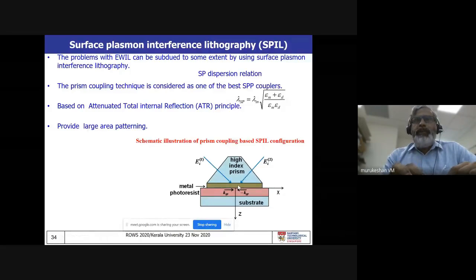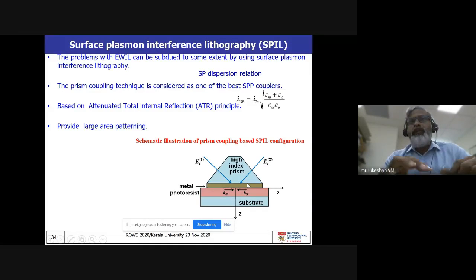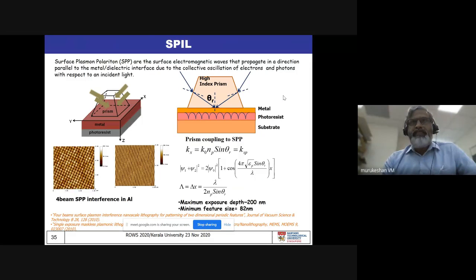What you are doing is that by counter propagating these beams, you are generating two surface plasmon waves, and you make them interfere. And remember, the surface plasmon wavelength is directly proportional to the epsilon m value of the metal as well as the dielectric. So by controlling this, we can control the wavelength as well as the pattern dimension based on this interferometric equation which is developed.